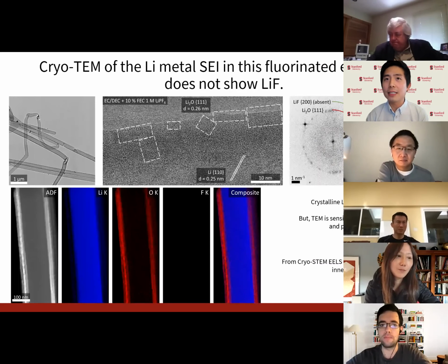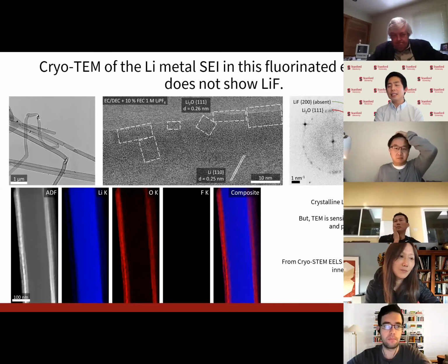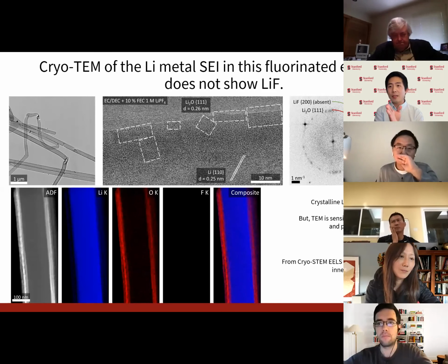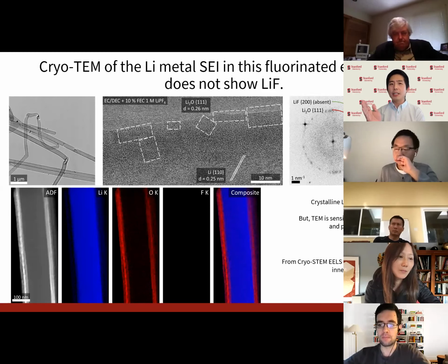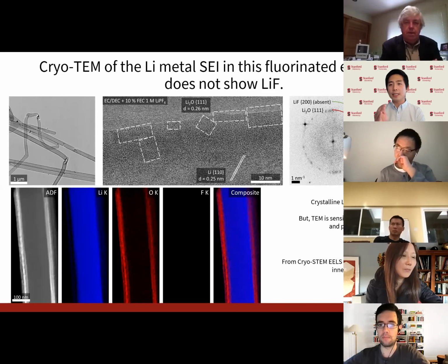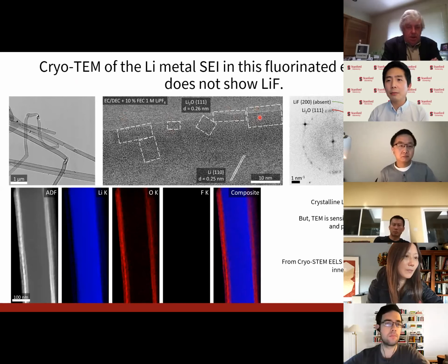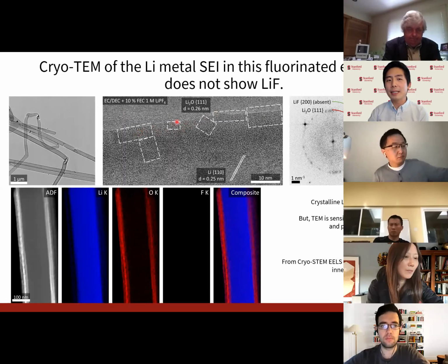And that's something I've spent a lot of time thinking about. So what Harry is saying is that this lithium metal study here and the silicon study both use the exact same electrolyte, that's the 10% FEC in ethylene carbonate and diethyl carbonate. But the SEI nanostructure changes significantly between the two. In the silicon case, we see a fully amorphous SEI, but with lithium metal, we see lithium oxide grains embedded within. And what we established previously is that this lithium oxide is coming from ethylene carbonate reduction.